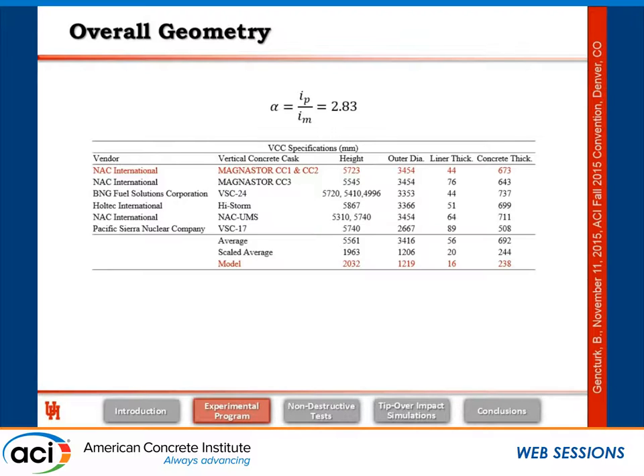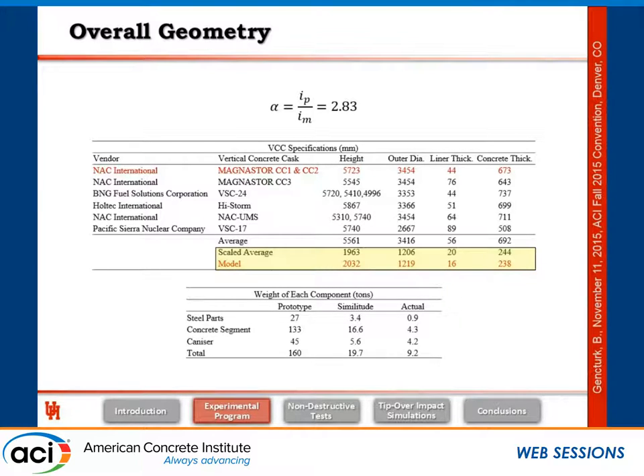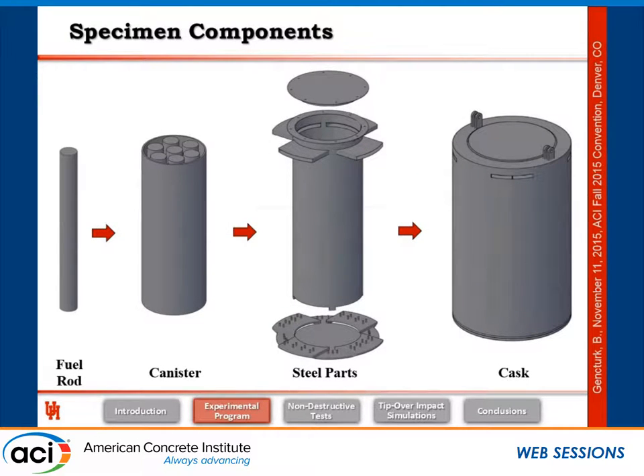Looking at the scaled averages for different concrete casks compared to our model casks, the key dimensions are quite close. In terms of weight, the prototype cask is typically around 160 tons. Applying similitude laws with this scale factor gives about 20 tons for the scaled model; however, due to limitations in concrete density, our model casks will be about 9.2 tons — simulating partially loaded rather than fully loaded conditions. We use steel rods to simulate the fuel elements, built a simple canister from a steel tube, and fabricated the steel liner, top air vents, base plate, and lid, simplifying some parts to ease fabrication.